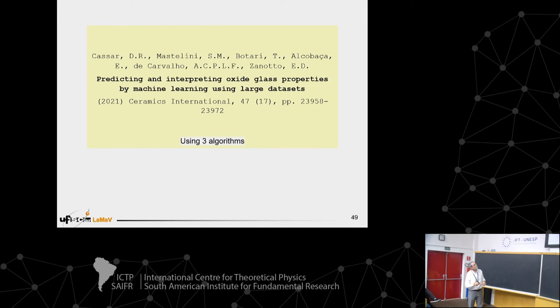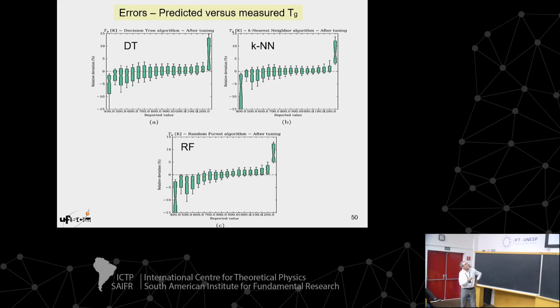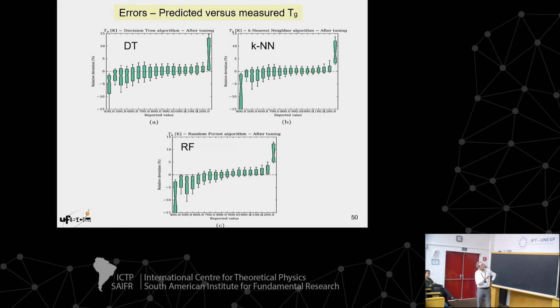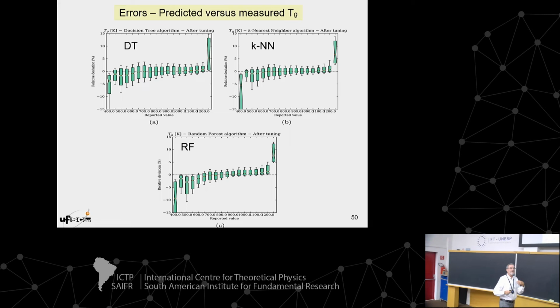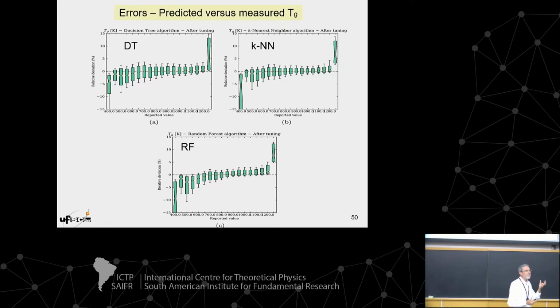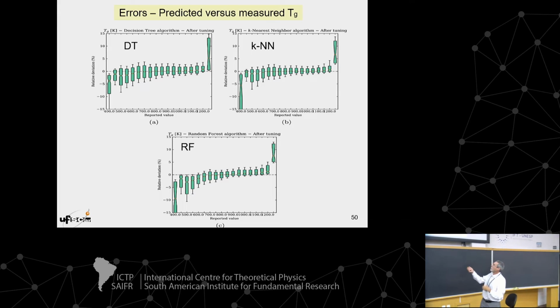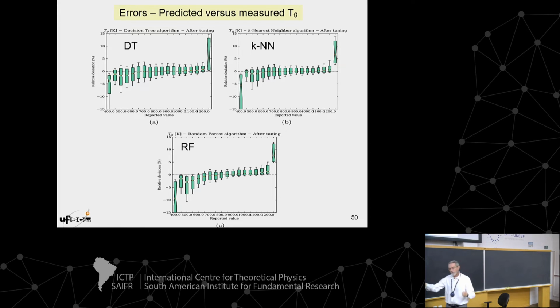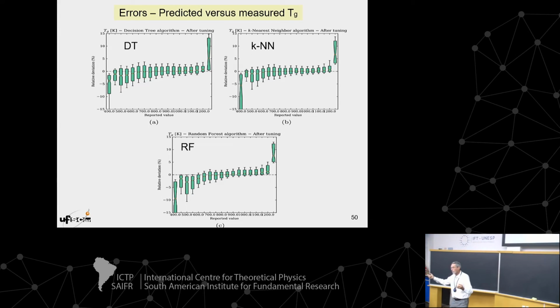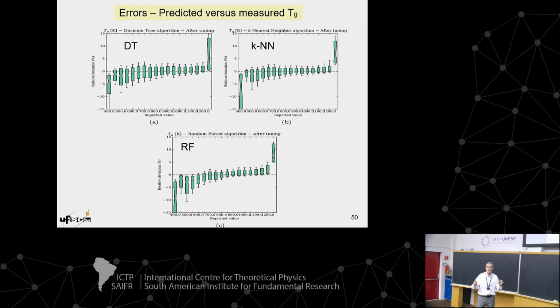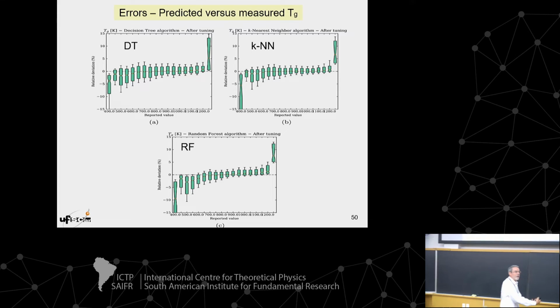However, the extrapolation ability, this is another way to show the error. Zero is very good, almost no error. But it increases here or here. For very low values of this particular TG, or very high values, the errors increase. So the extrapolation ability is not very good because of the poor training procedure. We had very good training for intermediate values of the properties, and very poor training for the limiting values of the properties, either too low or too high. So the quality of these results depends on the quality of the training.